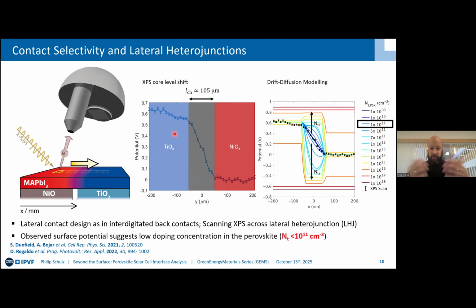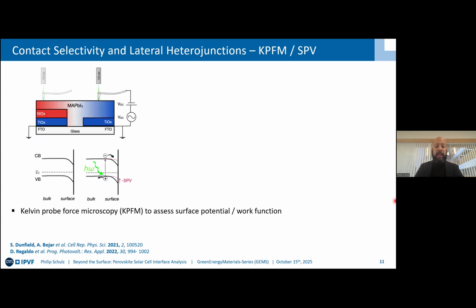And the initial model approaches were to simply take into account electronic effects. And then if you want to observe this change in surface potential, you can actually, but you need to go to very low doping concentration and also very low trap densities if you assume shallow traps, down to values that are below 10^11 cm^-3. So this would be quite astonishing, but it also doesn't really take into account ion migration effects or the interfaces really.